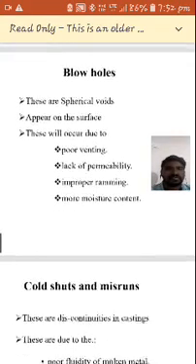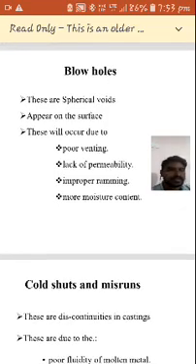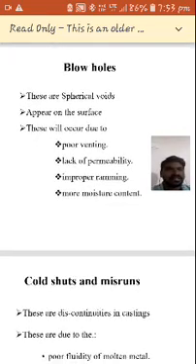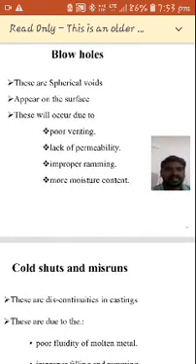Venting means that by using vent rods we make holes on the surface of the mold. The molten metal contains hot gases, and those gases escape through these vent holes. If the holes are not made properly, we get poor venting, so blowholes arise. One of the major causes of blowholes is poor venting.